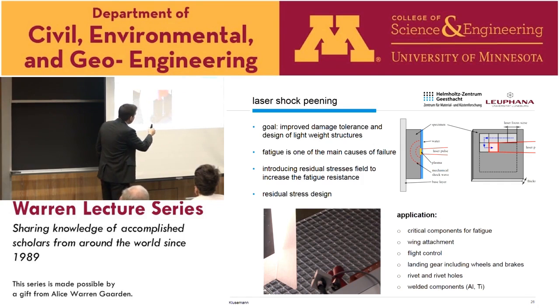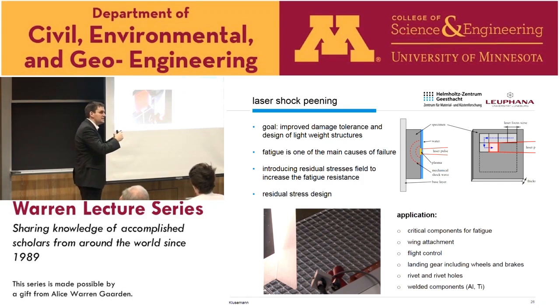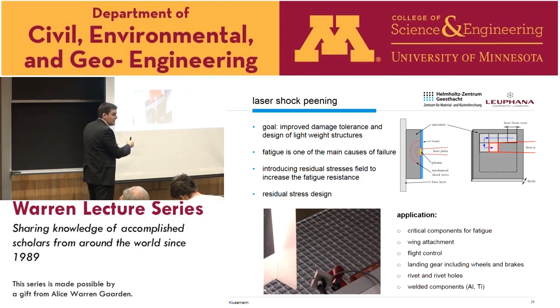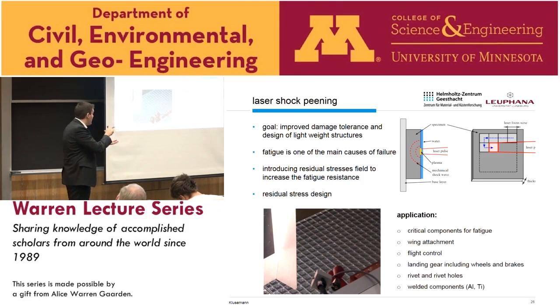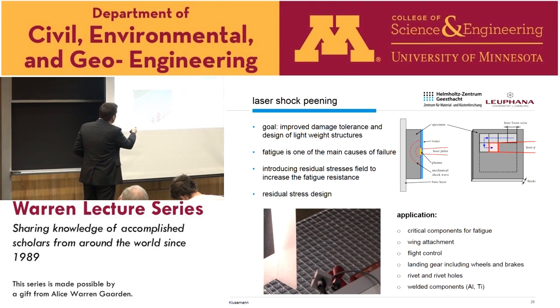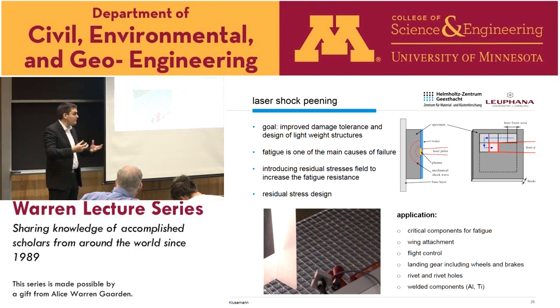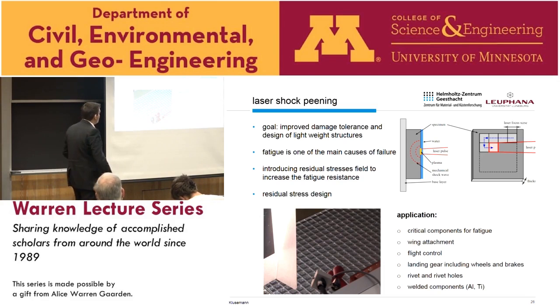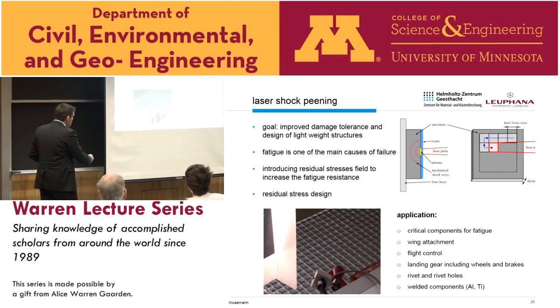So we have here usually a water layer or a foil. We have our laser pulse. And then this laser pulse penetrates our material. By this, it builds up a plasma. So we have some vaporization of our material, of course. We have here the water layer, which keeps the plasma under this. And then by this, we're introducing a shock wave or pressure wave inside of our material.